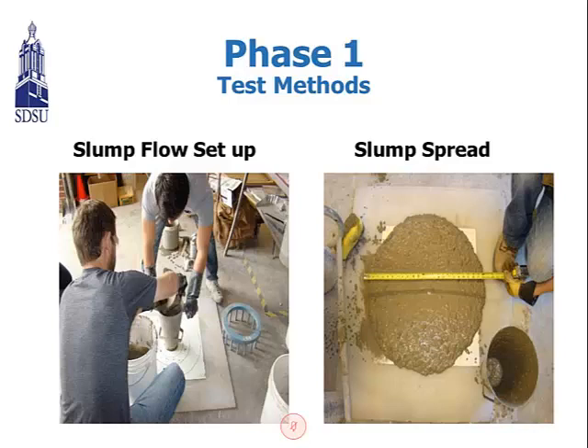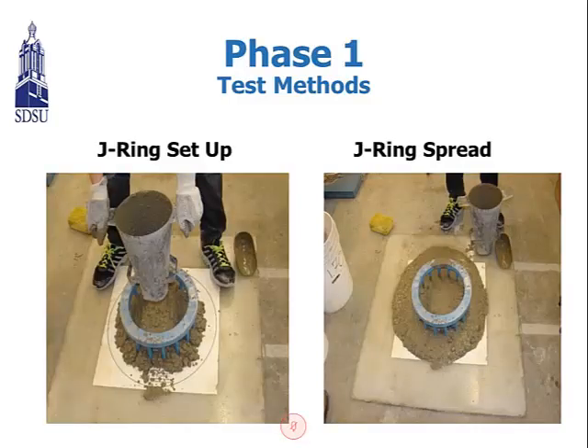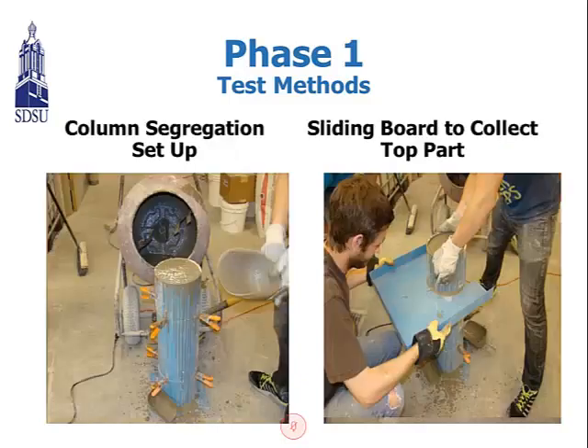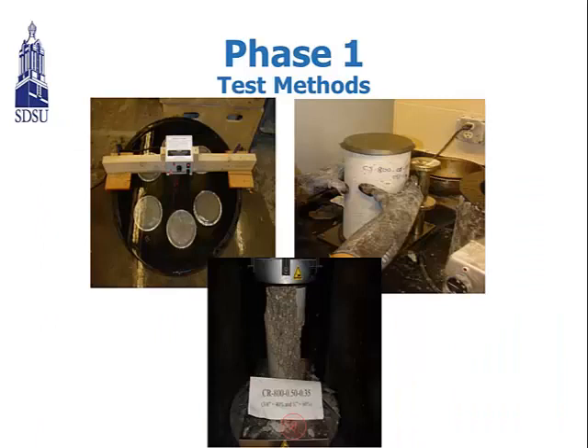So here are the phase 1 test pictures and test methods. Slump flow setup, you can see on the left side, and you can see the slump flow spread to measure the diameter of the slump spread. And here is the picture for the J-ring setup and the spread. And here is a picture for the column segregation setup and the sliding board to collect the top part of the column segregation. And here's a picture during the curing of the concrete specimens and the test for the compressive strength.